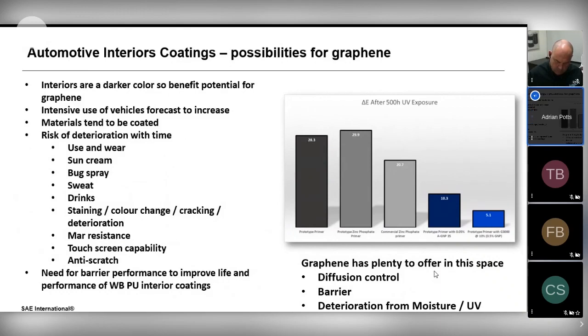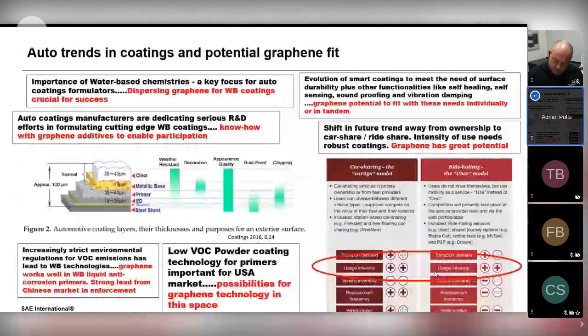Interiors tend to be a darker color, but we can utilize the barrier performance to really look at balancing chemical resistance and UV degradation. So graphene has plenty to offer in this space in terms of diffusion control, barrier, and deterioration from moisture and UV. Lastly, when we look at the future, really it's about use and abuse, we feel, and the need for